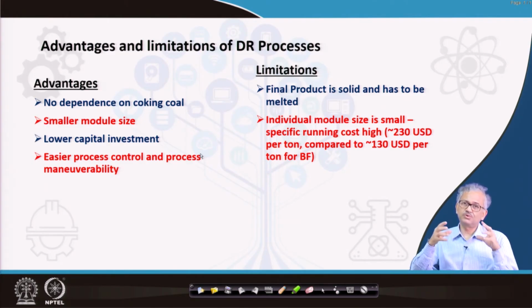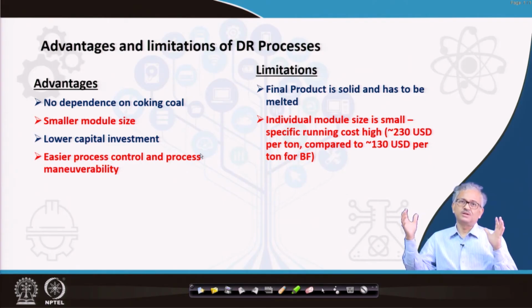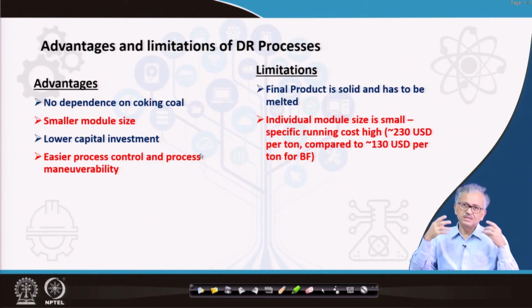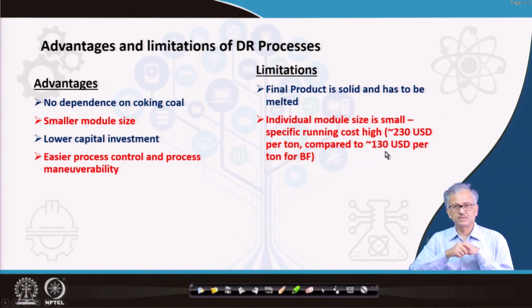Individual module size is not very large. Specific running cost is very high, and the specific running cost is high because you are not producing a large quantity. You are producing less because of size limitations. As a result, the specific running cost becomes high, for example, $230 per ton compared to $130 per ton of BF hot metal.